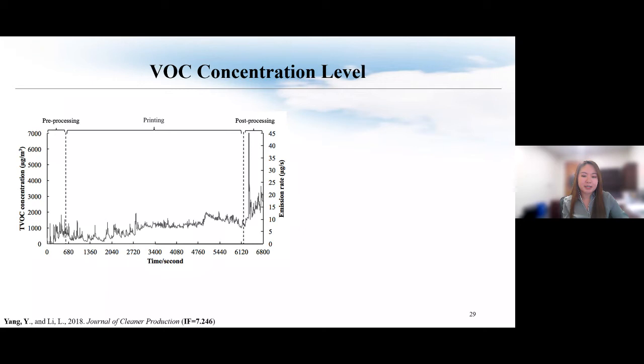Because after printing, I opened up the machine cover and took the part out. So I think what happened was that during printing, actually a lot of VOCs emitted from the resin, but they were trapped inside the machine because we have a sealed machine cover. And then when I opened up the machine cover, those VOCs were just suddenly released, causing this peak.